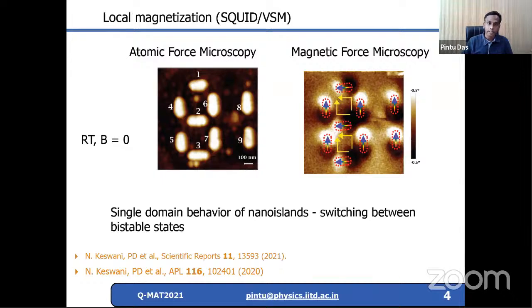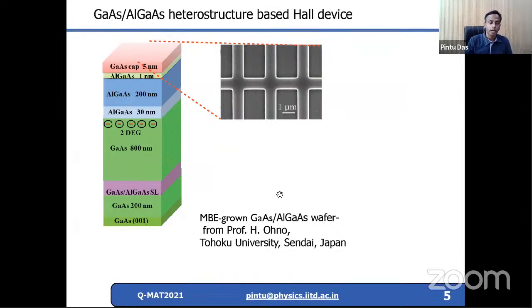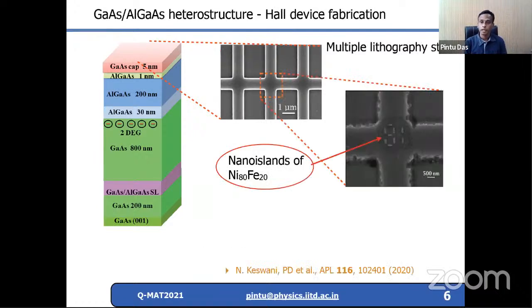Now, in order to understand this in detail, you need a highly sensitive tool, as I mentioned. What we have done is use a two-dimensional electron gas in the heterostructure of III-V semiconductors, namely gallium arsenide and aluminum gallium arsenide. We get these wafers from a collaboration with Professor Hideo Ohno at Tohoku University in Sendai. We pattern them in the Hall cross geometry and make Hall devices out of this, and then we use them to measure the stray field coming out of the nanomagnets. We pattern nanomagnets on top of that. These are wet etched, therefore the device doesn't look that nice, but it works nicely for us. You see the nine nanomagnets which have been patterned on top of the whole device to understand the switching behavior of these dipolar coupled nanomagnets.